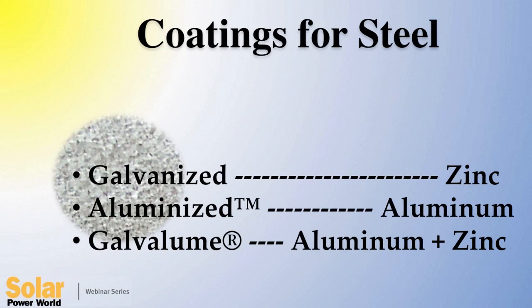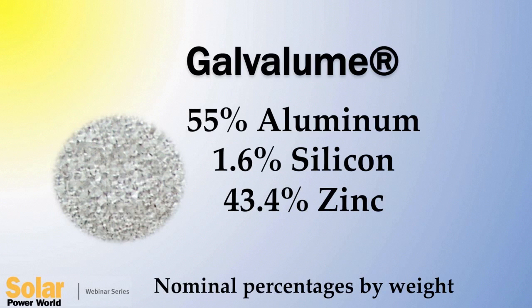Steel has to be coated, obviously, with some other more corrosion-resistant metal so that it prevents the oxidation of the base steel sheet. Popular metals include galvanized and aluminized. Zinc-coated, or galvanized, has been used for more than 100 years, and aluminum coated or aluminized has been used for about 50. But the most popular coating today is an alloy of the two, trade named Galvalume. That coating has been around now for almost 40 years. So if you're working on an unpainted steel roof constructed within the last 30 years or so, odds are very, very good that it's Galvalume.